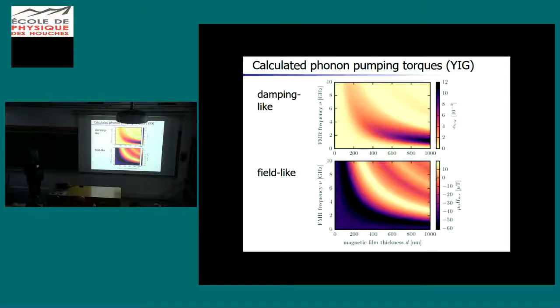Right, these are calculations done for the parameters of YIG, which might not be the optimal material because these magnetoelastic effects are pretty small. Nevertheless, what you see here as a function of the magnetic film thickness, and as a function of the FMR frequency, which can be tuned by a magnetic field, for example, we see that we have, first of all, these resonances I was talking about, at which the frequencies match the transverse phonons. And the maximum here becomes something like 10 to the minus 3, which is already quite relevant for very high quality YIG films.